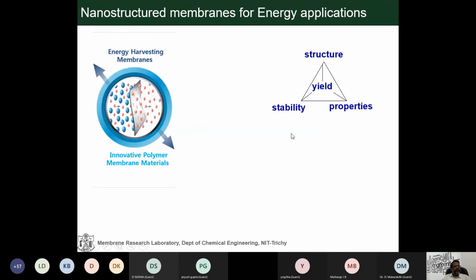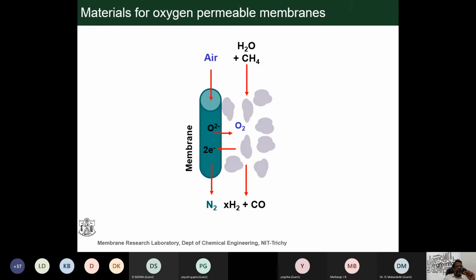See here, I told you about functional properties, well-defined structure, stability, and well-defined properties. These three properties give a good yield in membrane separation applications. Stability means that at higher pressure and higher temperature, the membrane should have stability. See here this membrane for oxygen permeable membranes. See, oxygen permeates through the membranes, and nitrogen and other molecules remain and move out of the membranes.